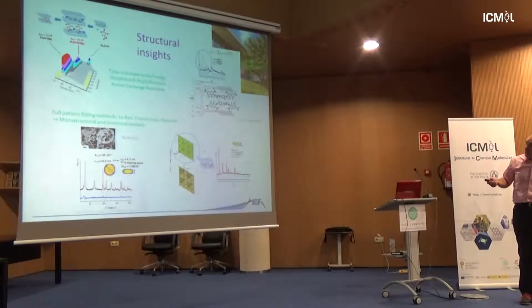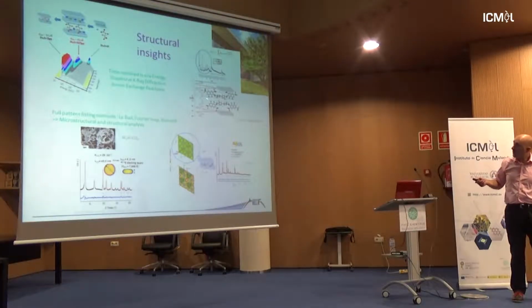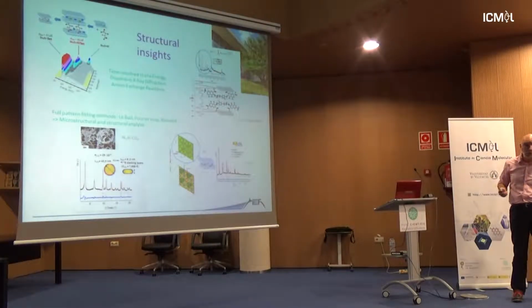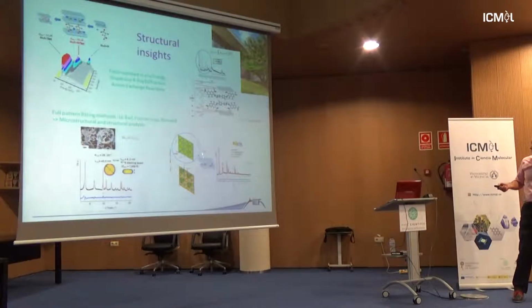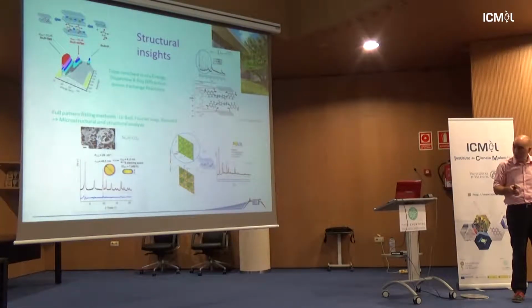And you have the exchange and the staging phenomenon that we observe on this copper chromium sample. We can do a 2D mapping, so 2D density in between the layers for this kind of molecule, to check if they have some gap in between, or if it's completely corrugated or conjugated in between the layers. So it's interesting to check the electronic density map as a function of the relative harmonic intensity that you can get after a Fourier transform of this X-ray diagram. And you can get as well, using Rietveld refinement, the anisotropy as well as the shape and the coherent length according to the X-ray analysis. And we also use different methods, like synchrotron in Paris, at Soleil, to do the pair distribution function. I will show you briefly after.